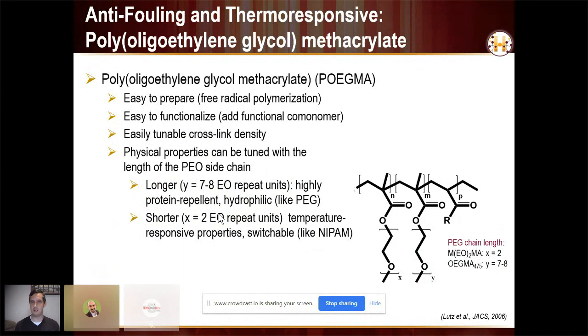I'll say PEGMA for the rest of the presentation for obvious reasons, as I trip over that. And this is a really interesting polymer because it has two key properties. One, the backbone is a methacrylate, so we can really easily prepare it through free radical or controlled radical polymerization strategies. But the side chain is polyethylene glycol. So what are the benefits of this? One, now that we can do free radical polymerization, it's really easy to functionalize the polymer. We can just add another methacrylate or acrylate to put whatever functional group we want inside this polymer. And this allows us to functionalize the polymer and also cross-link it and tune the cross-linking density by adding as many cross-linkable functional groups as we want.